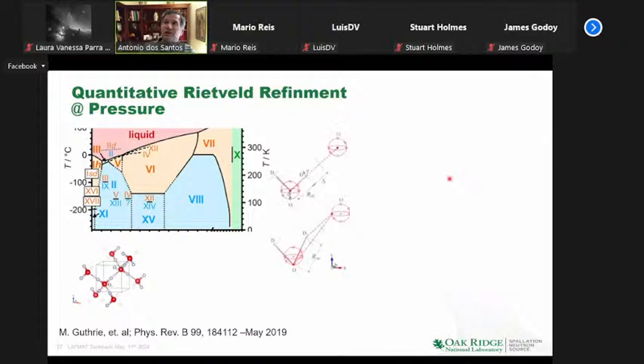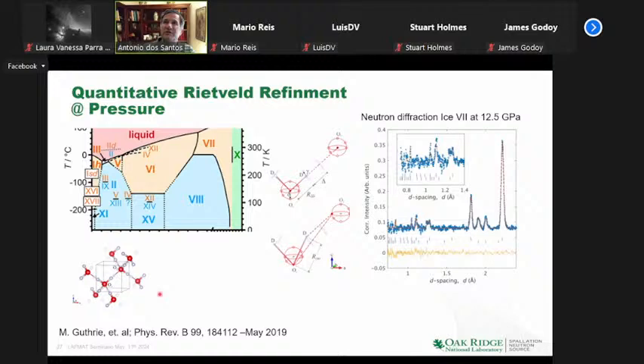I just want to say that even though it's water, this is a complicated refinement because the angle of the hydrogen or the deuteriums in water is different than the tetrahedral coordination of water in ice. And so you have a lot of atomic disorder, both on the deuterium, on these three possible positions, and the oxygen in these six possible positions. Despite that, this is how good of a refinement. This is at 12 GPa, but it's pretty consistent, and you can refine all the way down to 0.8. If you remember, the original powder pattern I showed you was stopped at 1. We can go to 0.8 angstroms in the spacing at over 10 GPa in water.